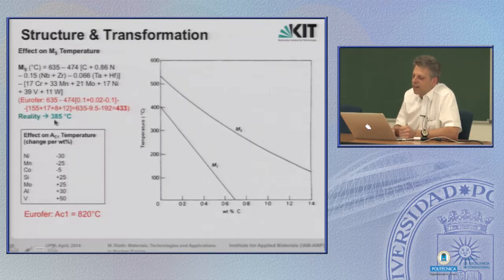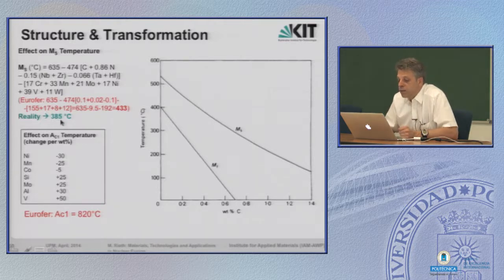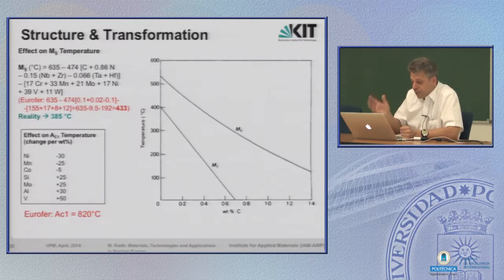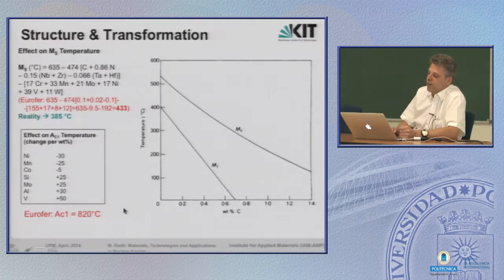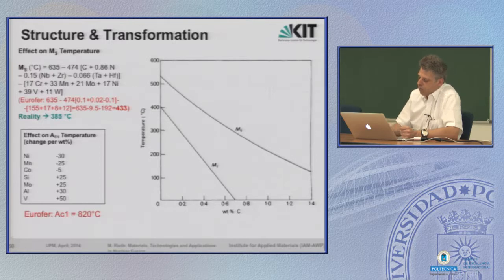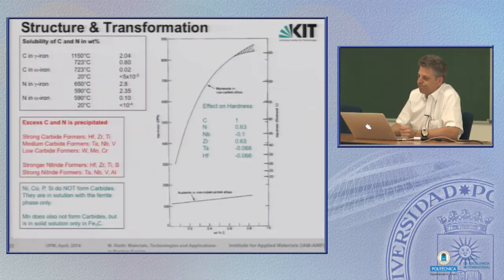In reality, the martensite start formation temperature is 385. So far to the rules and their applicability. Don't trust rules, but nevertheless, it gives you some rule of thumb for this material. The other important temperature is 820°C. When you heat up Eurofer, that's the transition from alpha to gamma phase.